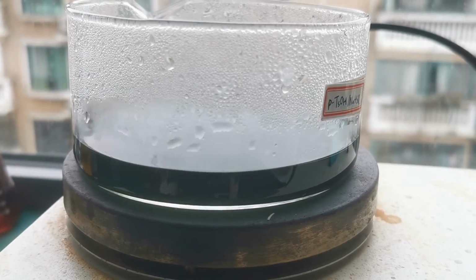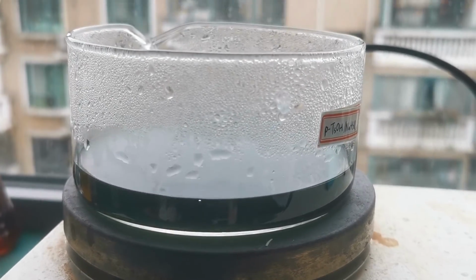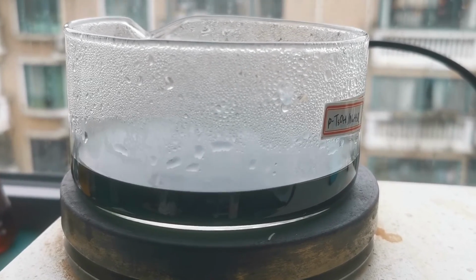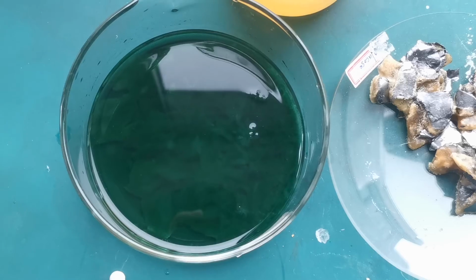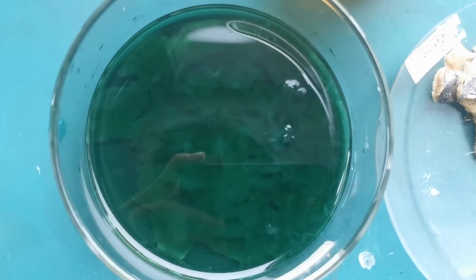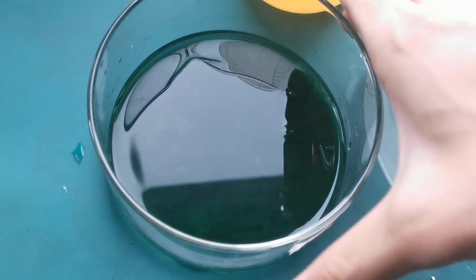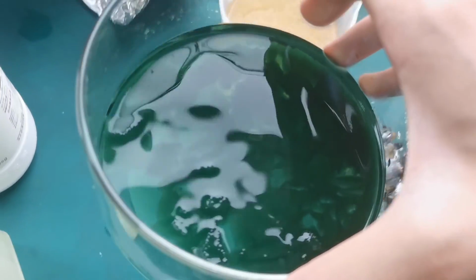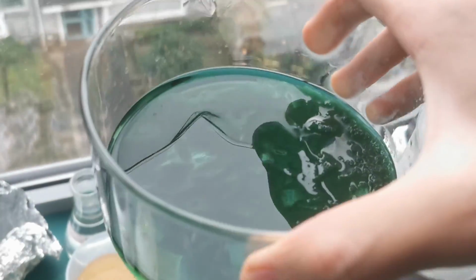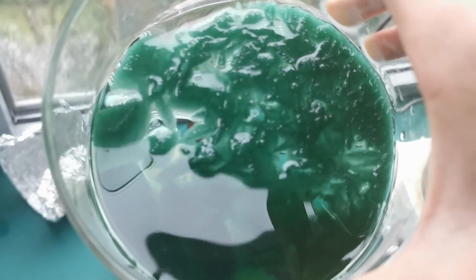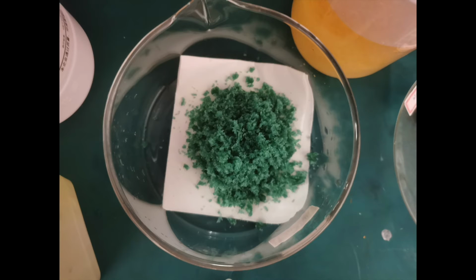The solution is evaporated in a crystallizing dish and removed from heat when its volume reduces to around 50 mL. When it cooled the next day, you can see the beautiful dark green crystals of nickel sulfate heptahydrate crystallizing out from the mother liquor. They're not exactly transparent, but I can grow beautiful single crystals from them. Those crystals are filtered and dried on a piece of filter paper.